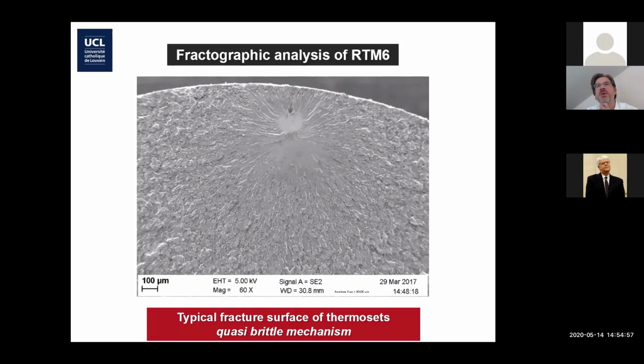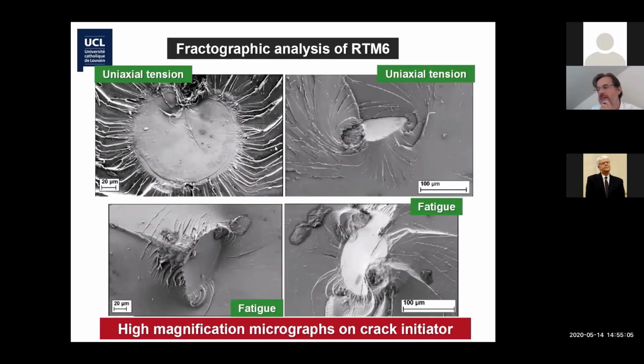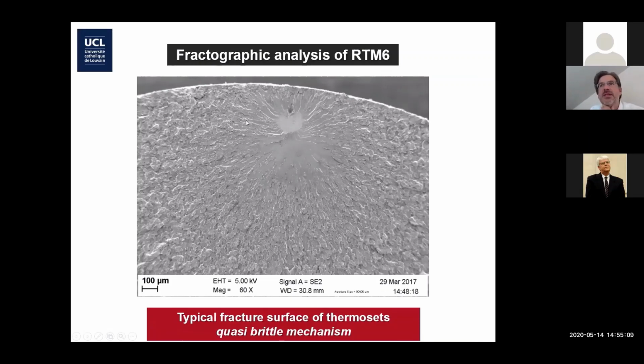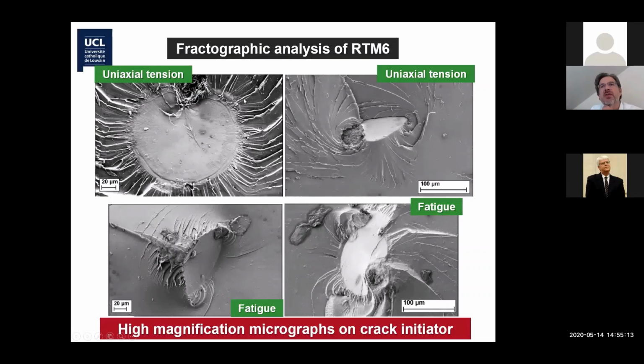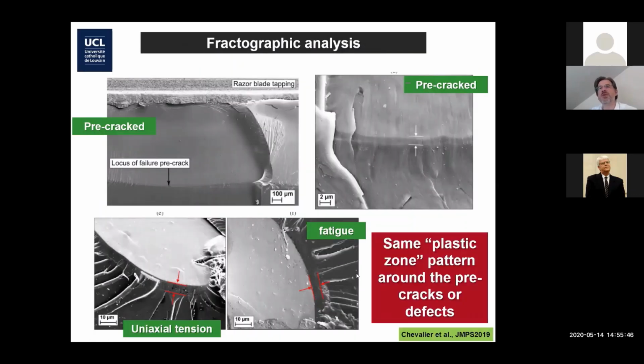I will finish by showing you some nice micrograph, fractography. This is RTM6 broken, and this is when you zoom in this initiation zone. And it's fairly interesting to see that you have a sort of defect. The defect is here, the defect is here, the defect is here. By the way, this is for fatigue and uniaxial tension, and we see very similar pattern in fatigue and uniaxial tension. Then around the defect, you have a flat region, a mirror-like region, and then you have a small, I don't know if you see it, but there is a very small narrow ribs of 2-3 microns here. And then you get the brittle failure pattern with the river lines. If we zoom in along this flat plateau, and I'm looking below here, you see this plastic zone. We think it's a plastic zone, and we have reason to believe.